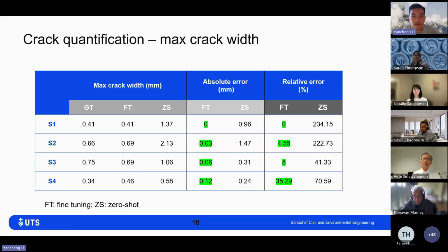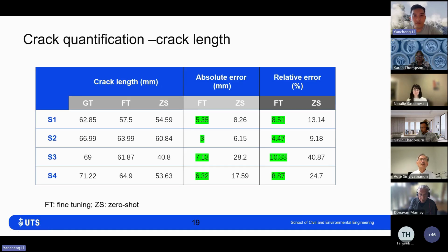This is the max crack width, where we have the widest part of the crack. You can see our result is also pretty good in terms of absolute error and relative error in percentage. So we are quite okay in that sense. We are also able to measure the crack length based on the image, and a similar pattern is shown over here. Imagine it's not like you have to measure one by one. Once you have this algorithm trained, you simply input an image, and the algorithm tells you the crack width, crack length, etc. We are also able to detect crack depth, but of course it's not the aim of this project, so I didn't show it here.